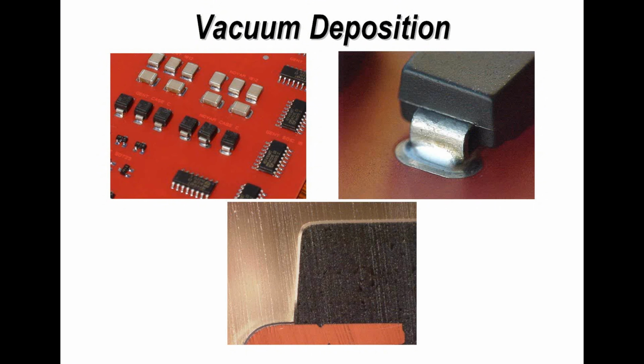And I've shown you here three examples. Three photographs on this slide illustrate a board that has been coated with parylene. And in all honesty, when you look closely at the surface, you really can't tell that it's actually been coated. It takes a lot of experience, and I, for one, find it difficult. On the top left-hand view, you can see a board assembly. On the top right view, you can see a close-up of a solder joint, and really there is no obvious sign of a coating being present. However, in the third view, the microsection view, you can see the coating quite clearly as a grey line around the part.